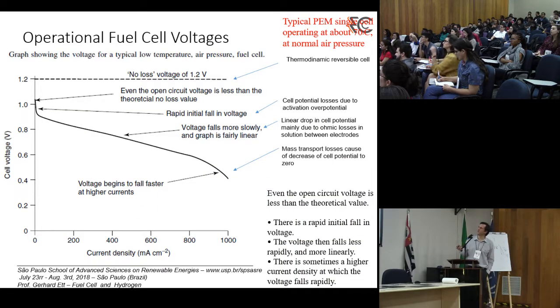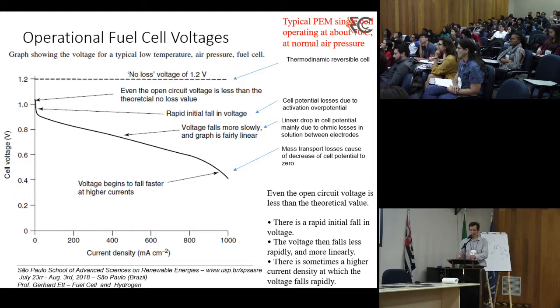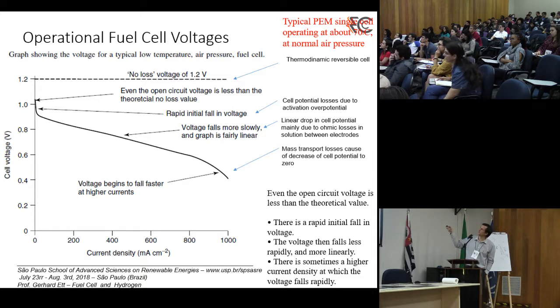Here is the typical polarization curve of a cell. Here we have tension, and here we have current density. This is a typical curve. With this curve, we can analyze the measurement of the current and tension of this membrane. Here with no losses, the voltage is at the maximum, 1.2, for the thermodynamically reversible cell. Then, at the beginning, the tension goes down very fast. This is the activation overpotential, a rapid initial fall in voltage.